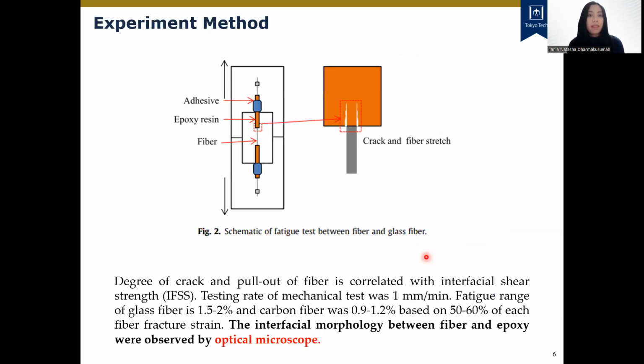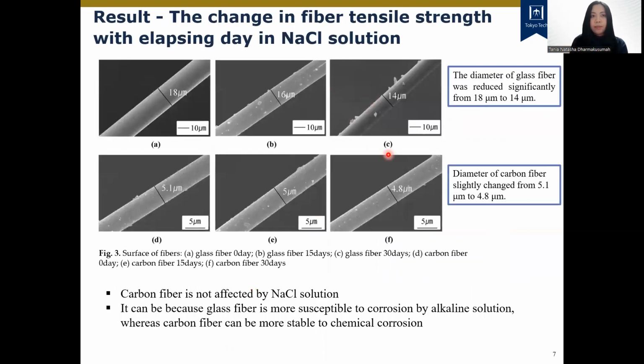For the experimental method, after we made the specimen, we put it in this, like a schematic of a fatigue test. We put the epoxy resin and also the fibers, and we want to know about the crack itself. By this optical microscope, we can see the interfacial morphology between the fiber and the epoxy matrix itself. After elapsing in NaCl solution, we observe the tensile strength.